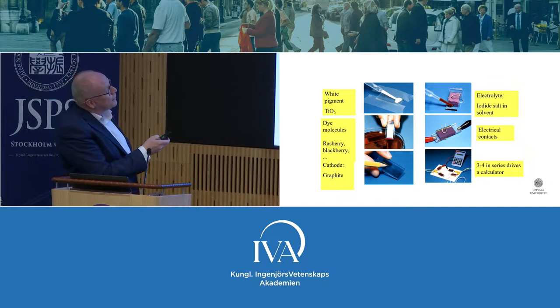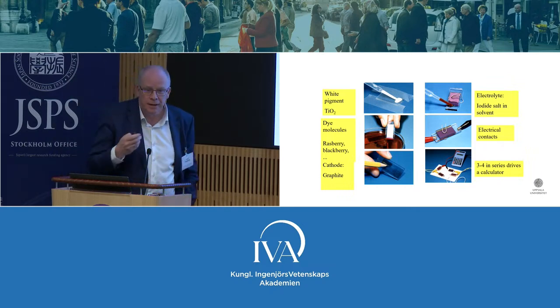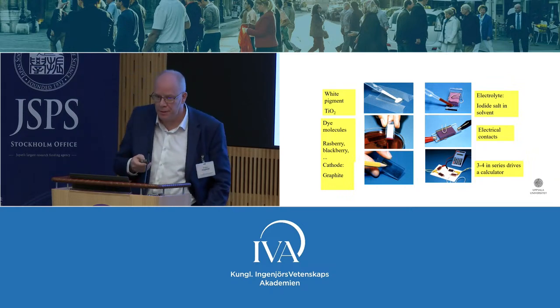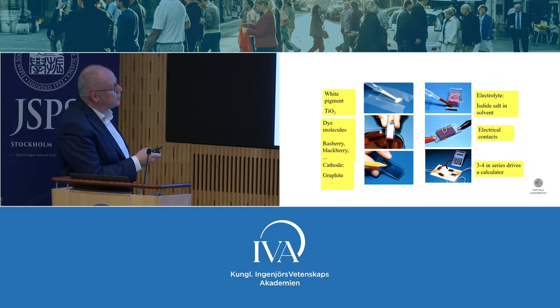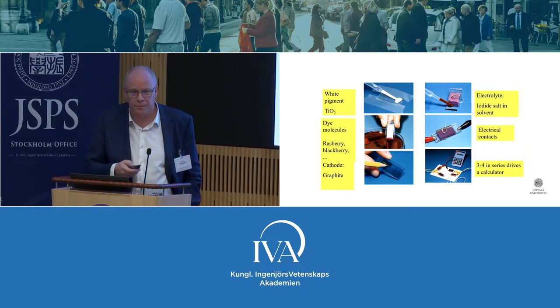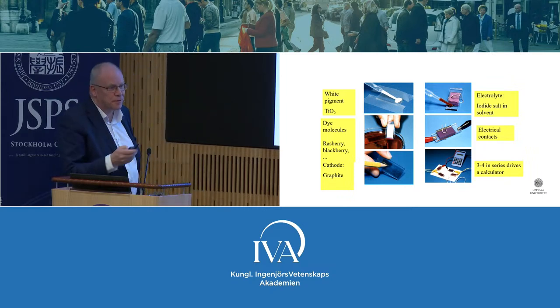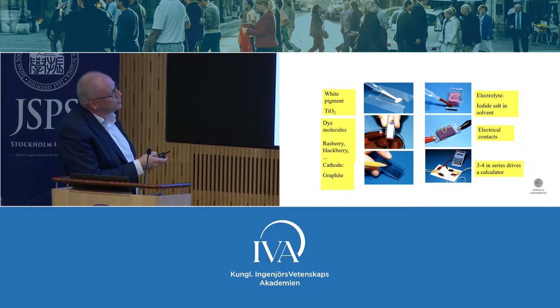You start with your conducting glass. You put the scotch tape for the film thickness and to have the contacts here. You have a solution of the titanium dioxide nanoparticles, which you deposit and spread out. You heat it up. That's a step here with a fan. And then you take your electrode into the dye solution. This is the fun part of the lab, because the students have to find their own dye molecules. You can try raspberry works well, blackberry works even better, strawberries not so good, for example. Now we saw coffee also can work. So you can try a lot of these things. The cathode is done by graphite from the pencil. So then you have your photoelectrode and the graphite, and you fill it up with electrolyte and clamp it together, contacts, and you have your solar cell made.